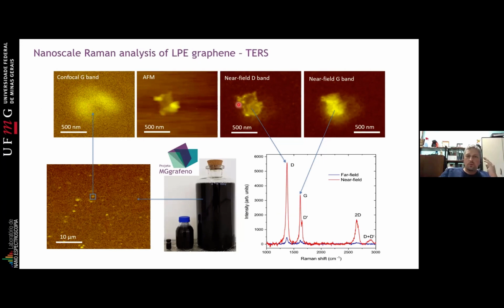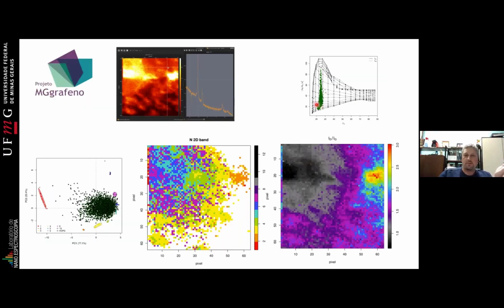So we can do this nano-Raman and improve the spatial resolution a lot, and we can take hundreds of spectra inside the flake and analyze it locally. This is completely different. We are now analyzing the flakes, the chemistry, the functionalization, and so on. This is another example, from software that we developed for the NanoRaman. This is a lot of graphene flakes, but the image is only 150 nanometers by 150 nanometers. This would be completely blurred in a conventional system.